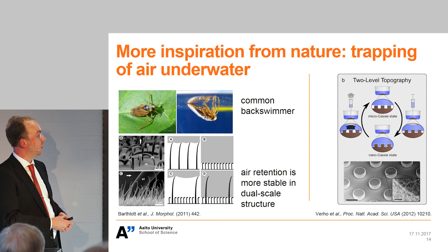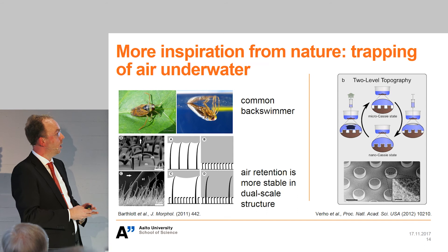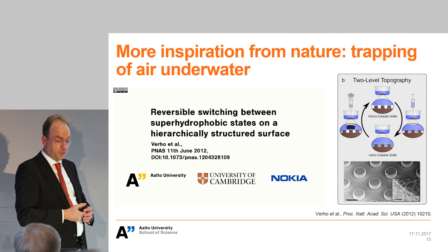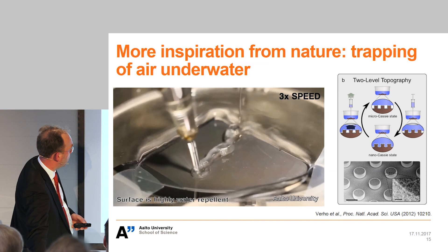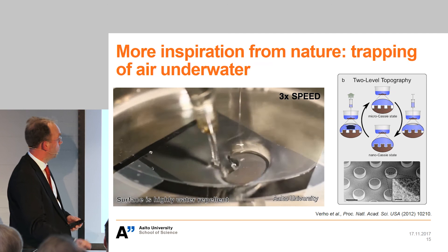This nanoscale structure makes the surfaces very stable — the air layer is very stable on these structures. When we apply pressure, water fills in between the pillars, but we can reverse this by suction because the air layer is still present. You can see this in the video: the surface is at the bottom of a tank, filled with water — it is very repellent. A thin air layer is trapped on the surface, and we write on it with a jet of water underwater. This causes a wetting transition and a change in optical reflection, and this is a reversible process — we can also erase the written structure.